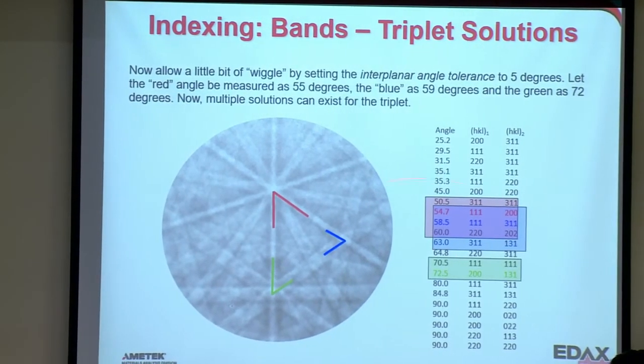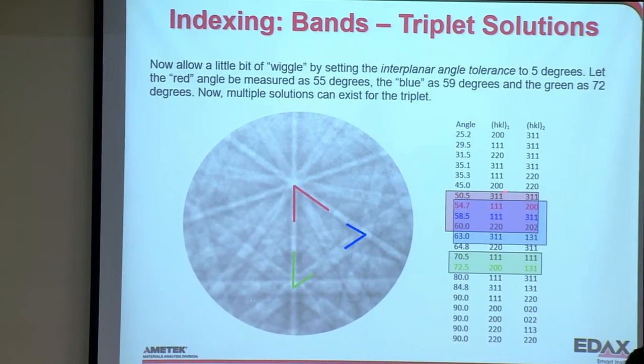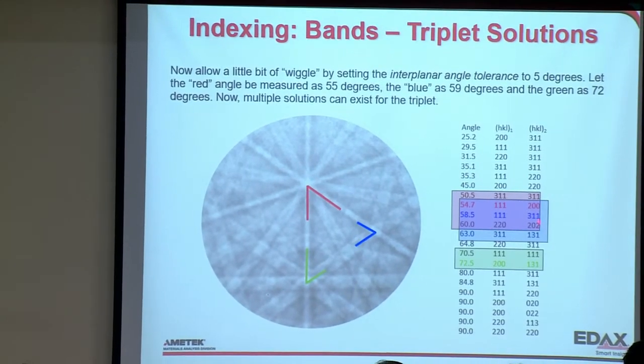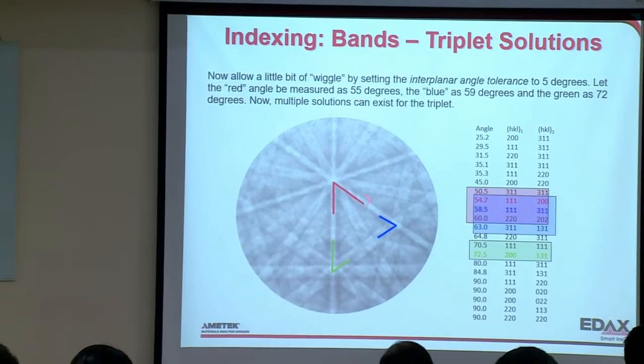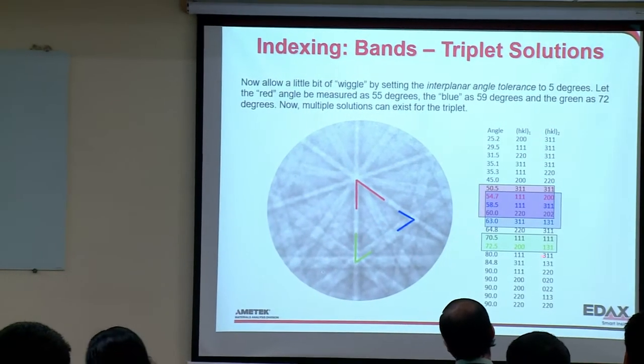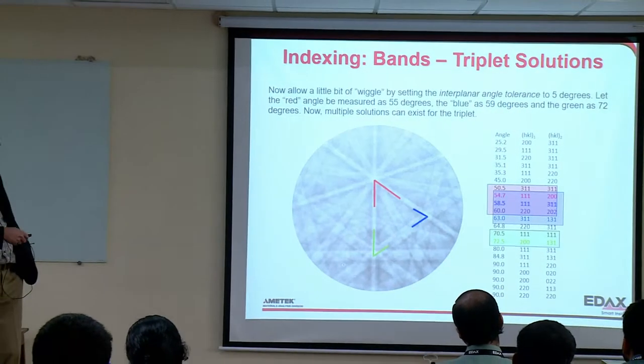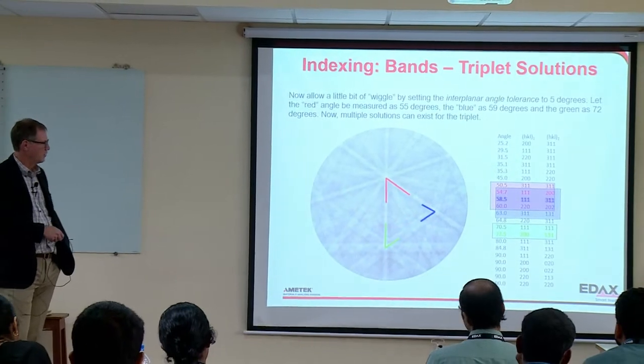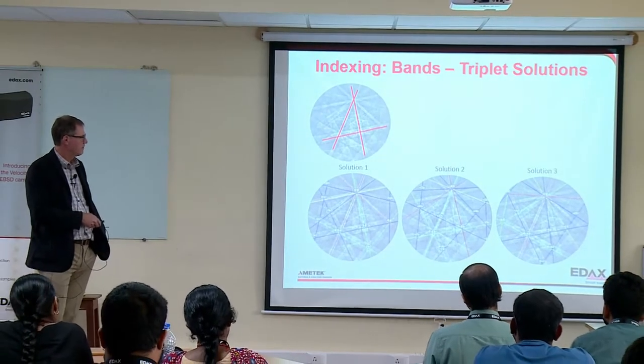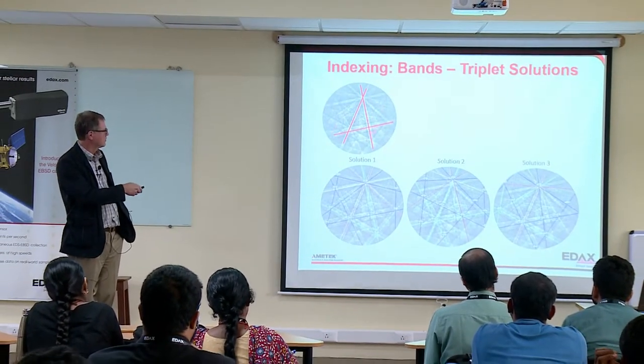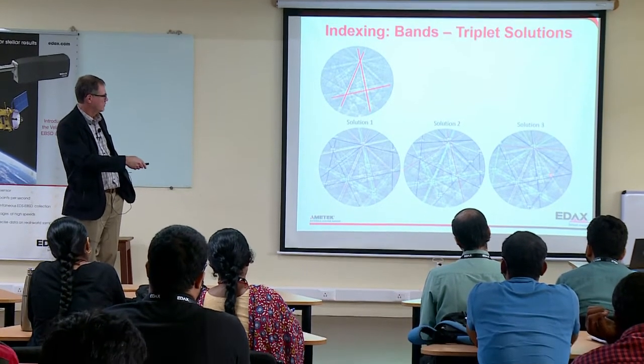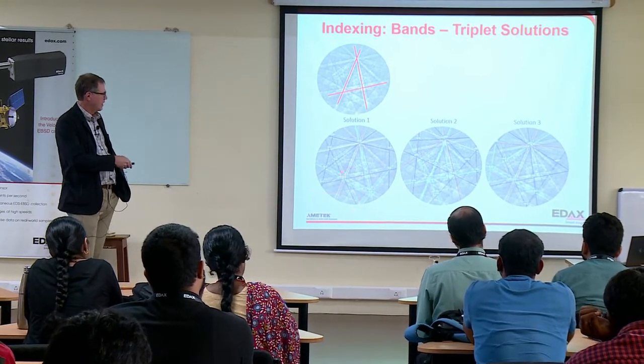And like I said, we can get those within, say, 2 to 3 degrees. This is if I use a tolerance of 5 degrees. You can see there's 4 possibilities for the red, 4 for the blue, 2 for the green. But if we apply our triplet argument, then we can reduce that quite a bit. In fact, there's only 3 possible solutions for these 3. This one, and this one. But you can see this is the right one.